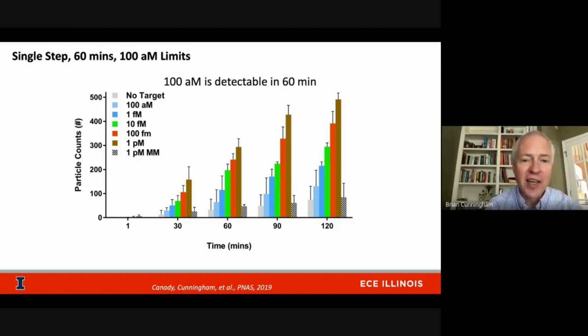What this showed us is that 100 attomolar limits of detection were achievable after a 60-minute incubation time. And so here, if I just focus on the 60-minute mark, the gray bar represents no target present. This is our non-specific attachment of nanoparticles that land on the surface by gravity. We also had another type of negative control where we had 1 picomolar concentration of microRNA that differed from our target microRNA by only 1 base.